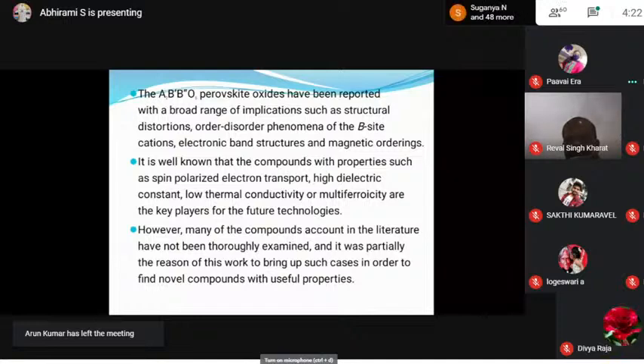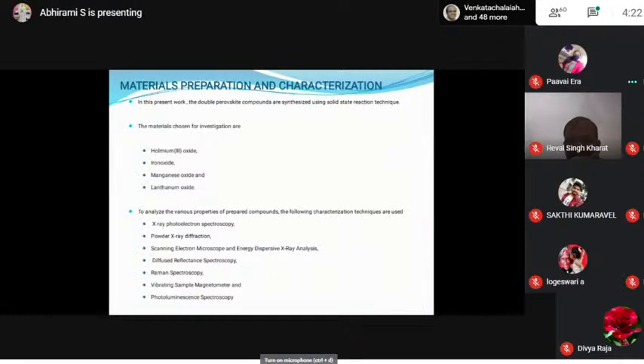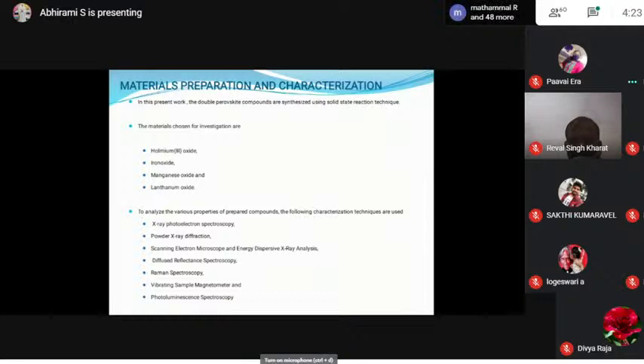However, many of these compounds reported in the literature have not been thoroughly examined, and it was partially the reason for this work to bring out such cases in order to find novel compounds with useful properties. So, materials preparation and characterization in this work. I am taking holmium oxide, iron oxide, manganese oxide, lanthanum oxide. Also, to analyze the various properties of the prepared compounds, I am using X-ray photoelectron spectroscopy, powder X-ray diffraction, scanning electron microscope, energy dispersive X-ray analysis, DRS, Raman spectroscopy, vibrating sample magnetometer, and photoluminescence spectroscopy.